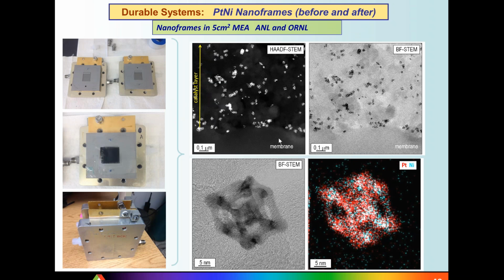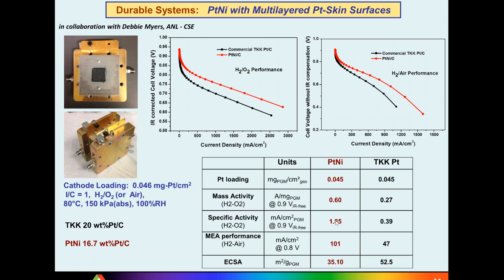Also, here is a snapshot of how those advanced catalysts such as nanoframes look before and after MEA treatment. So they do preserve shape, and they also preserve the compositional profile, having that platinum skin on the surface. Another example, in addition to nanoframes, and actually our intention was to start the scale-up effort with simpler systems such as solid platinum nickel nanoparticles with multi-layered skin, and we already obtained results that are currently matching whatever numbers were obtained from nanoframes just for a one-shot experiment, and right now we are in a position to produce gram amounts from a single batch, and